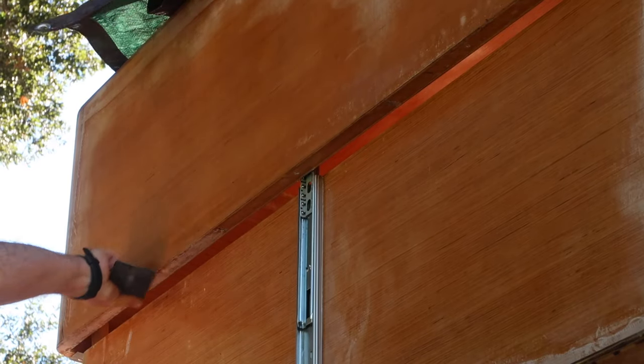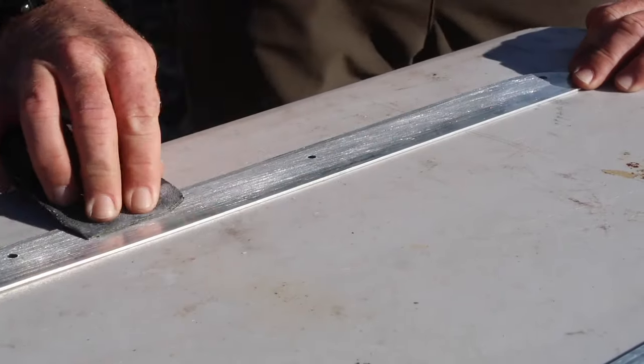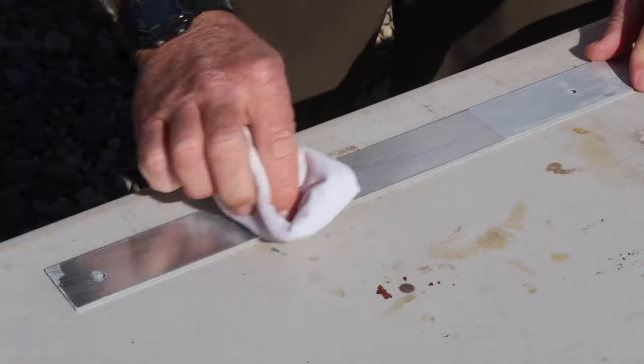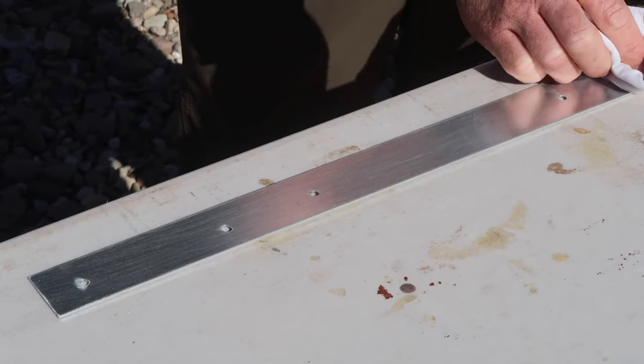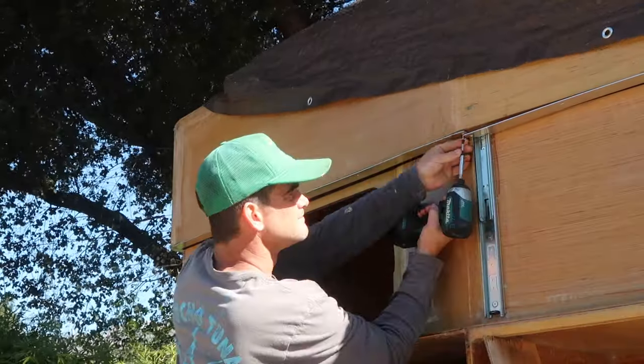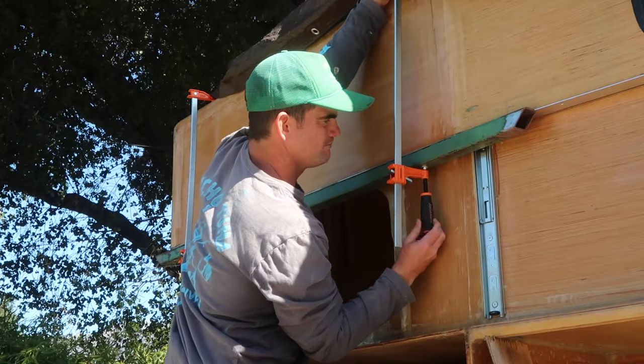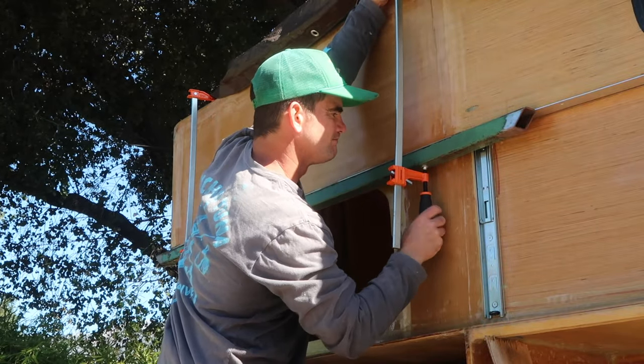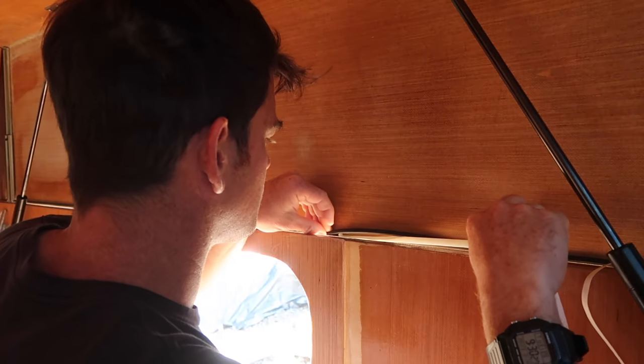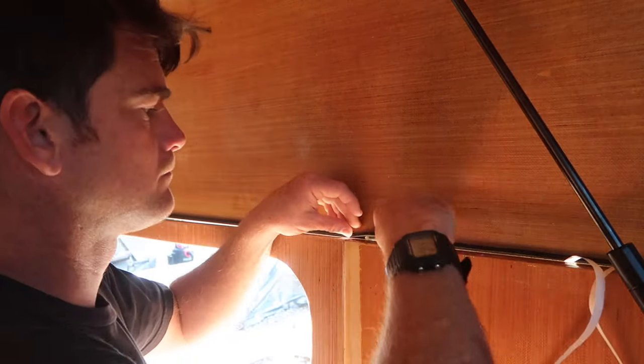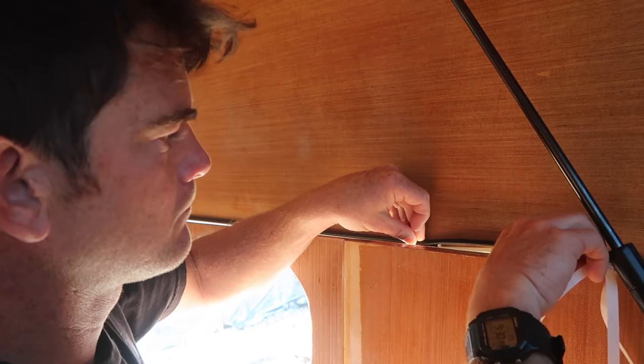The edge of the pop-up and each piece of aluminum were roughed up with 80 grit sandpaper and cleaned with denatured alcohol to help adhesion, and clamps with a piece of scrap steel were used to compress the thin aluminum into the adhesive. Once that was completely cured, I applied a D-shaped foam rubber seal with an adhesive backing to the top inner part of the aluminum flat bar. This was easy to cut and install. The most time-consuming part was just cleaning the aluminum with denatured alcohol.